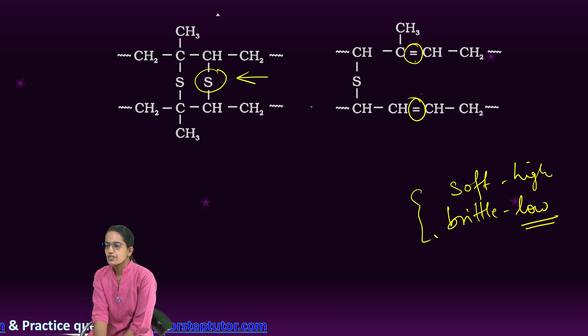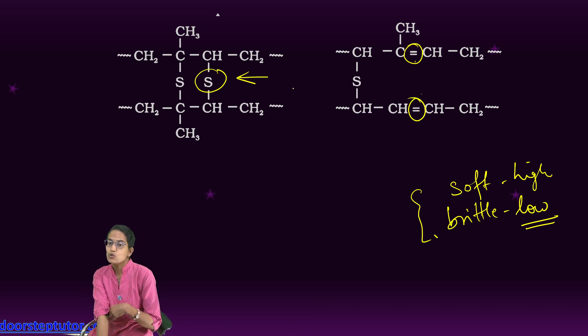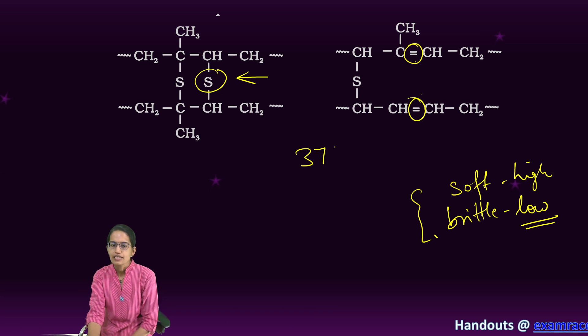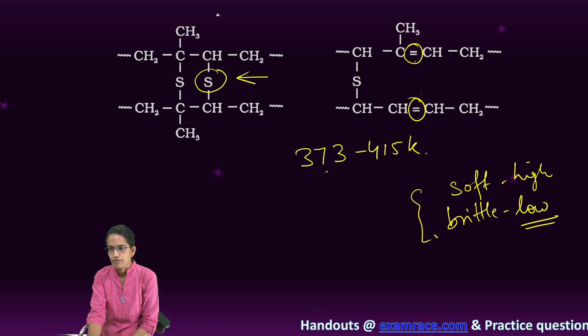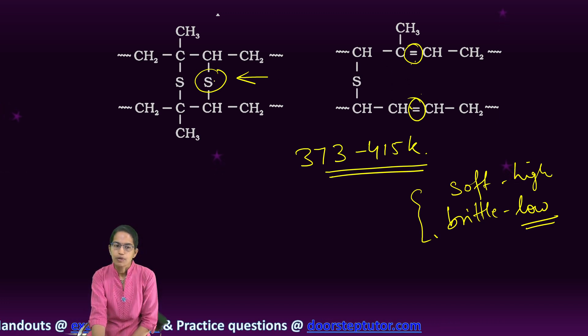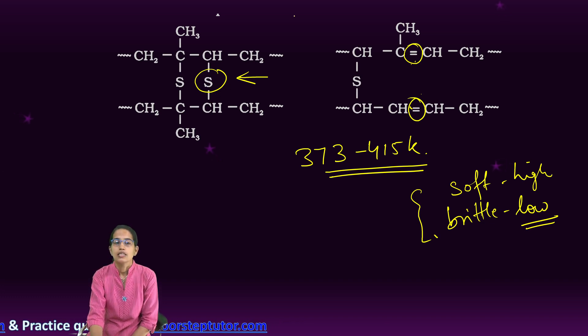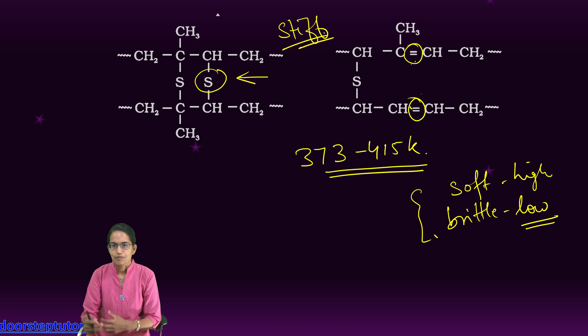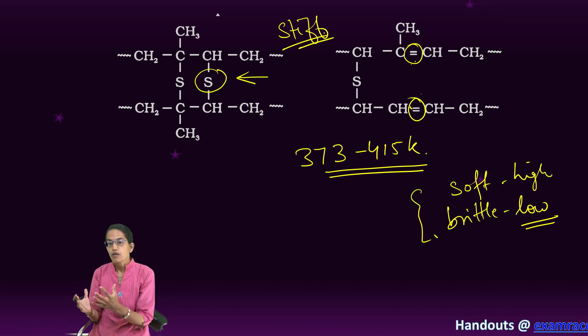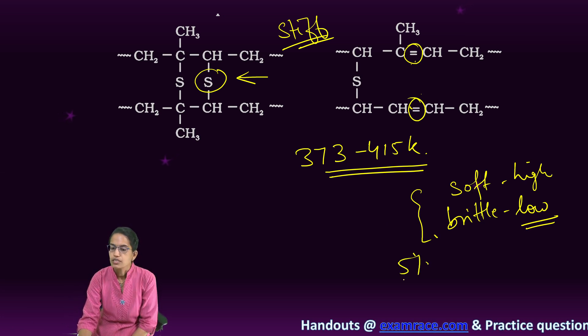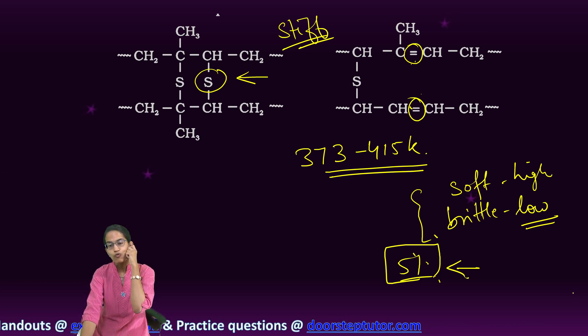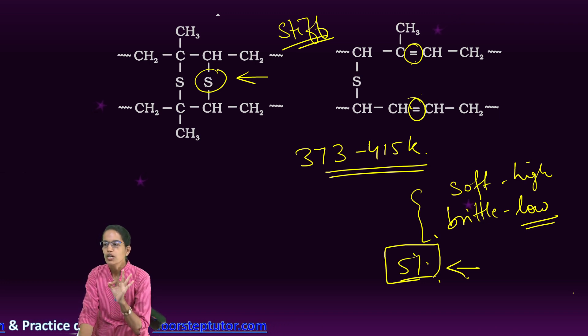This process is known as vulcanization. The rubber is heated with sulfur at an adequate temperature range of 373 to 415 Kelvin, and the reactive double bond sites are bonded. Rather than double bonds, you have sulfur cross-links present. This sulfur gives rubber a stiffer characteristic — it becomes more stiff. For tire rubbers that are manufactured, 5% sulfur is added, and this leads to vulcanization.